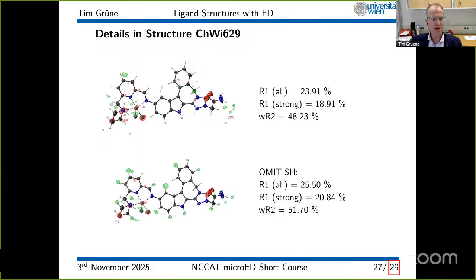This is what the structure looks like. You see, it's a metallo-organic complex. It's coordinated by 2 chlorine atoms, which is interesting because in electron diffraction, you would expect that you have quite strong beam damage. Technically, that's not the case. I'm not going into the very details about this. Again, the R values that you find here are relatively high for a small molecule structure. 24% of an R value, that's outrageously high. But you see from the structure that it's correct. The nice or convenient thing about chemical crystallography is once you solve the structure from direct methods, you know that you have solved the structure correctly, and you just need to do the fine printing work. With protein structures, you have to be more sophisticated for proper validation of your data.